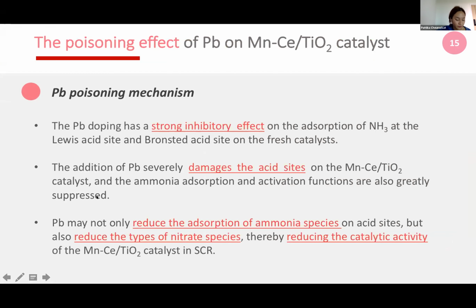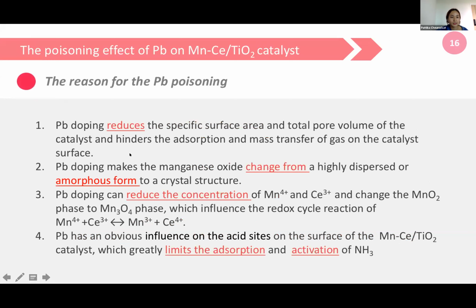Pb poisoning mechanism. Pb doping has a strong inhibitory effect on the adsorption of ammonia at the Lewis acid site and Brønsted acid site on the catalyst. The addition of Pb severely damages the acid sites on the catalyst, and the ammonia adsorption and activation functions are also greatly suppressed. Pb may not only reduce the adsorption of ammonia species on acid sites, but also reduce the types of nitrate species, therefore reducing the catalytic activity of the catalyst in SCR.